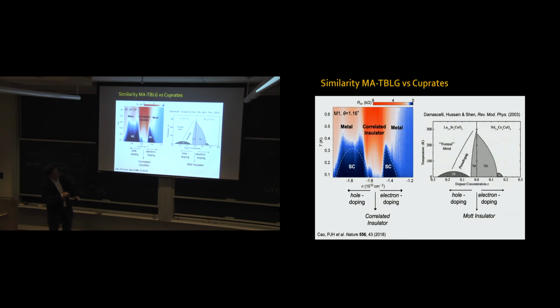Now it's correct. At half filling, they have a Mott insulator state, with 0 doping meaning 1 electron per site, actually. The doping is relative to that state—0 means 1 electron per site, half as many electrons as you can put. If you add a few extra electrons, you get a small superconducting dome. If you add a few extra holes, you get a large superconducting dome.